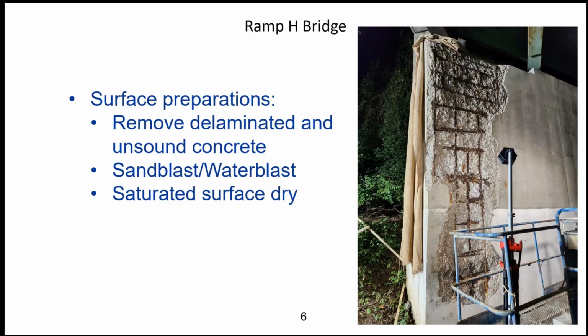So this is a close-up after the preparation, where you could see all the loose and damaged material has been removed. The steel is exposed, and the bridge is ready to receive the spray-applied UHPC. And again, one of the main preparation steps is the saturated surface dry condition, where the concrete is prepared to receive the spray applied UHPC. Next slide, please.